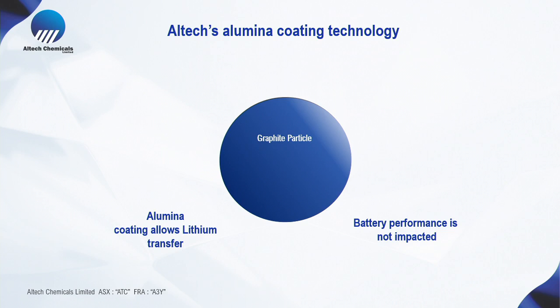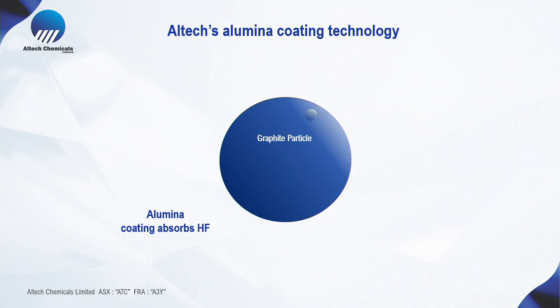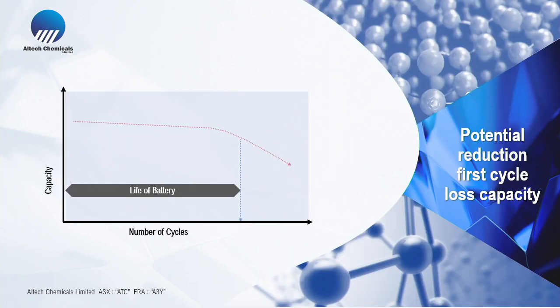And the other great thing about our alumina layer, we believe, is that it'll start absorbing the hydrofluoric ions. It absorbs the hydrofluoric ions and converts them to an inert material. So the degradation of lithium going forward is minimized. So we look at the graph again and we say, if we can resolve this first cycle lithium loss, this is what the performance should look like.